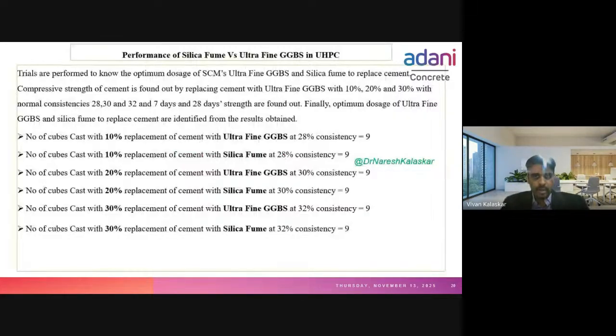A small experiment we have done, where we have created mortar cubes. In those mortar cubes, we have replaced 10% cement with ultrafine GGBS, and 10% cement with silica fume. I think you people know how to test the Indian standard mortar cubes, like for cement grade test, 200 grams of cement and 600 grams of Indian standard sand. Same thing, same study we have done.